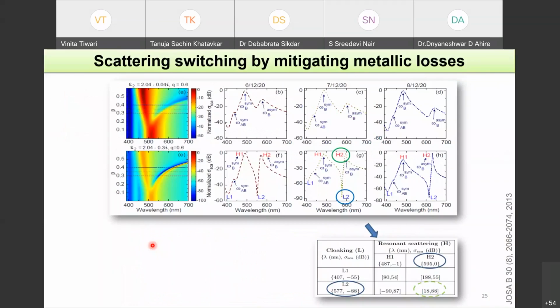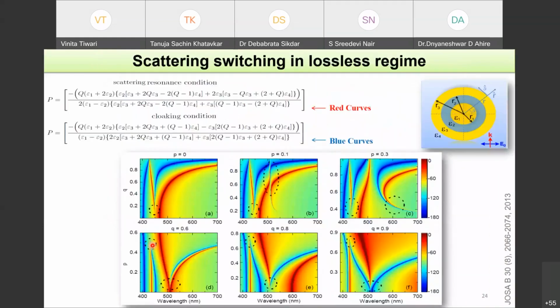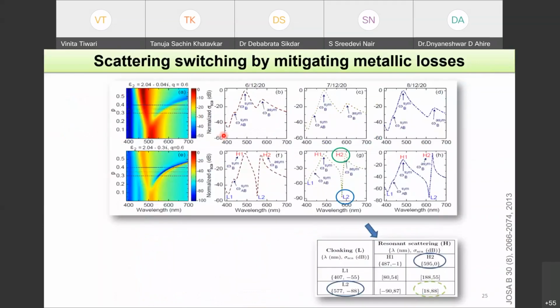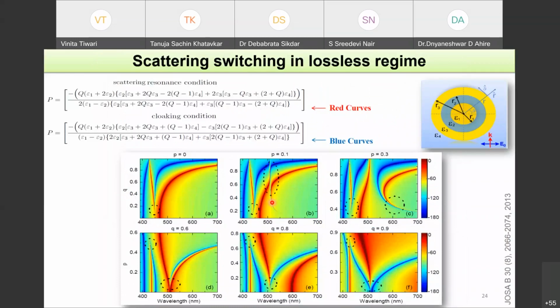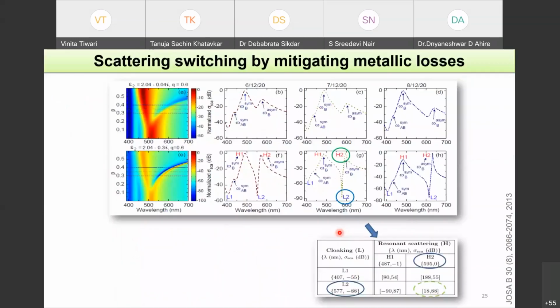Now, life comes with some difficulties. Similarly, all these metallic structures, they will come with some losses. So when you consider the losses in your calculations, you see that those sharp dips and peaks are getting disappeared. They're all getting broad, and the dip is getting shallower, peak is also getting shorter. So to restore such good performance, what you have seen here is basically done in lossless regime where we consider metal to be lossless. So when you come back and consider the metal in its original form, that the metal is lossy, but then you do something to incorporate that loss or compensate that loss.